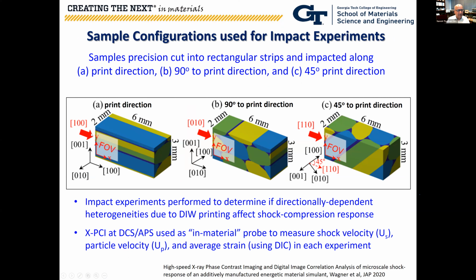In this schematic A, the impact is along the print direction, which we label as the 100 direction. In another orientation, we machined it so the impact is 90 degrees to the print direction, based on the contours of the individual layers. Finally, we machined sections so the impact is along 45 degrees to the print direction.